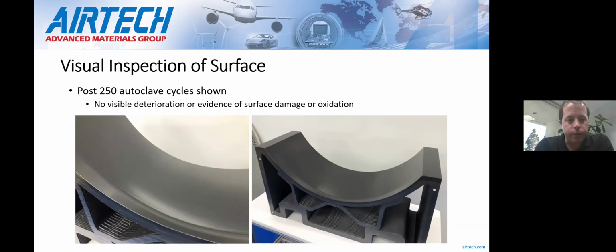Also looking at things visually. This is the tool after 250 autoclave cycles. You can still see that it's got a really good surface finish and it's holding up well, with no visible deterioration or evidence of any kind of oxidation or surface damage.